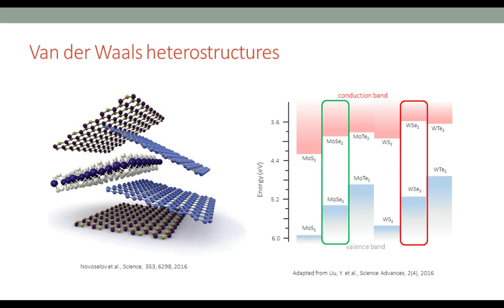So the TMDs come in many classes as well. There's molybdenum and tungsten for the transition metals, and sulfur, selenium, or tellurium for the chalcogen layers. If you make these different materials, you can see that their band gaps are varied, and if you align them, you can see that certain materials will form either type 1, type 2, or type 3 junctions. In our case, we're very interested in making a type 2 heterostructure. So we chose MoSe2 and WSe2 as our materials to place on top of each other.